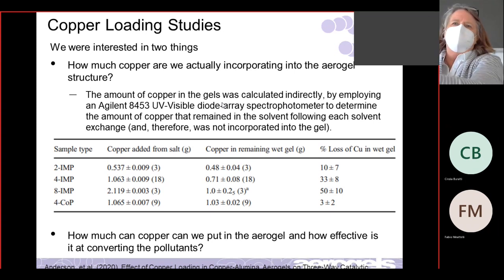So we used a spectrophotometer to determine how much copper stayed in the solvent and didn't go into the aerogel or the wet gel. And we were able to do that by mixing up concentrations of copper, of known concentrations of copper in ethanol, and measuring its spectroscopic at a certain wavelength. We could calibrate, come up with a line that says, you know, if the intensity is 20, you have 2 grams of copper. If it's 40, you have 4 grams of copper, something like that. So we were able to do that.